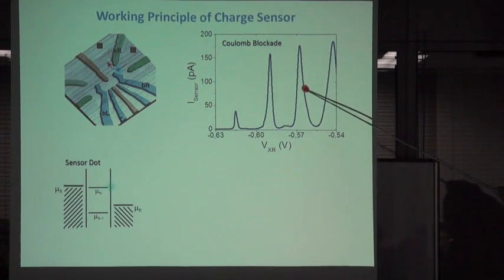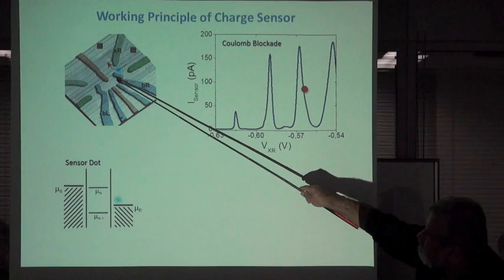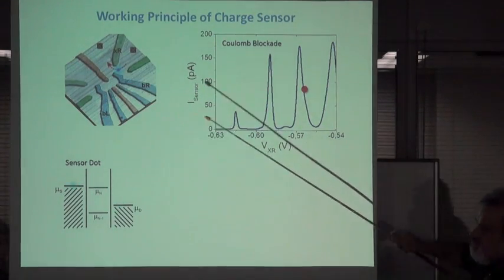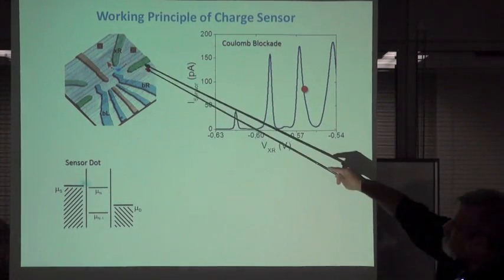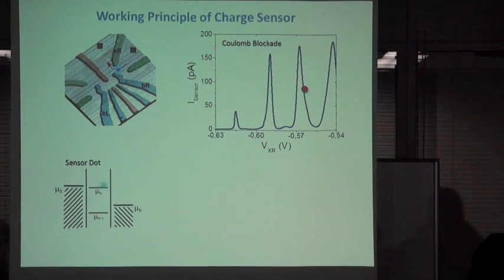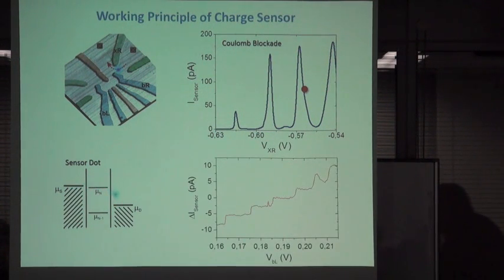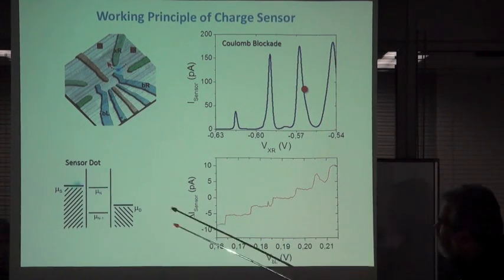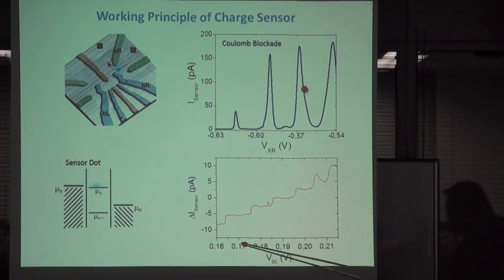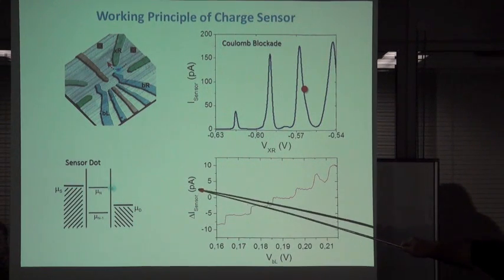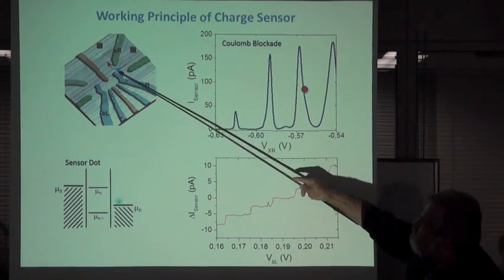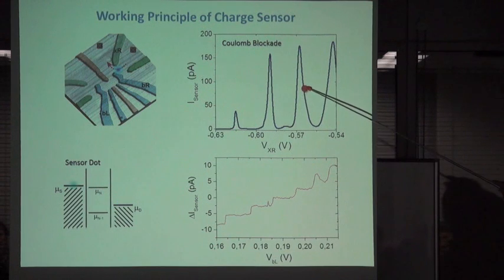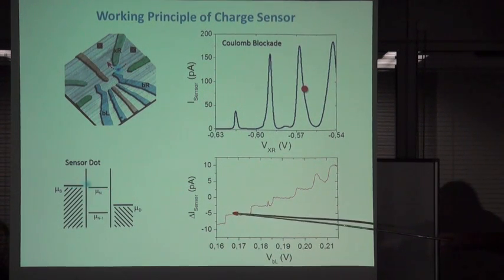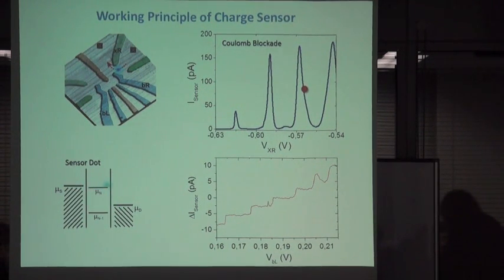And here on this slope, this is very sensitive for charge. If I add a charge here, this will be seen by this point contact here. And that's what we are using. With respect to the left gate here, we change the left gate in a certain range, and we measure the change in the current through this point contact when we sit on this slope, and then you see each extra electron coming into the dot by this change in the sensor.